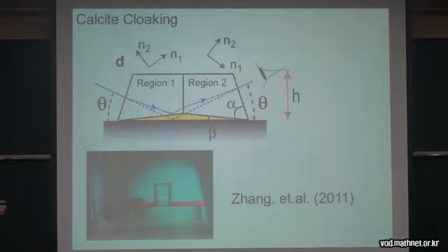And then later it was realized in 2011 that one could get much simpler cloaks. In particular, just a piece of calcite would do the trick. And the idea was to use a deformation which was piecewise constant, and which mapped this region here into the region with this vanishing, actually. And so this was just a constant anisotropic dielectric tensor here and a constant anisotropic dielectric constant here, which could be mimicked by crystals of calcite. And so here you've got a pink rod which is being cloaked by the calcite, actually.